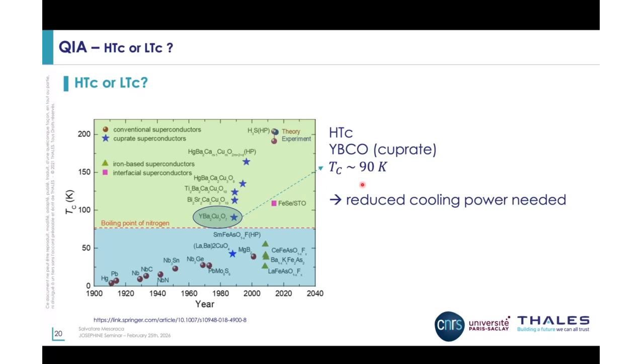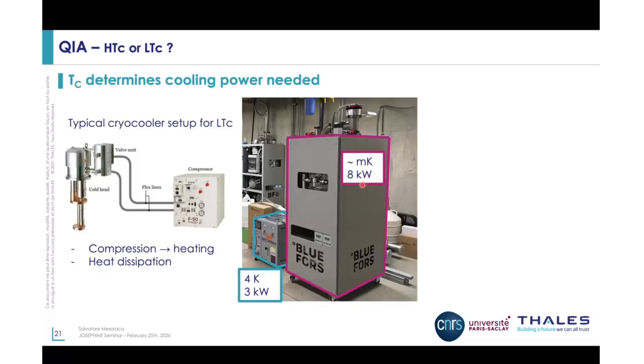And that means that we can use machines that have a reduced cooling power. What do I mean by that? If you look at the systems usually needed to cool down low TC superconductors, in the range of 4 Kelvin or even lower, millikelvins, we are obliged to use very big, very heavy machines, not only in volume and weight, but also in energy consumption. They consume from 3 kilowatts to 8 kilowatts. And as I said, they have a big SWaP factor, so they are big machines.